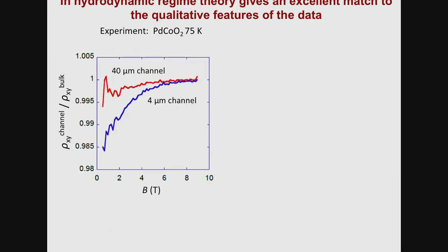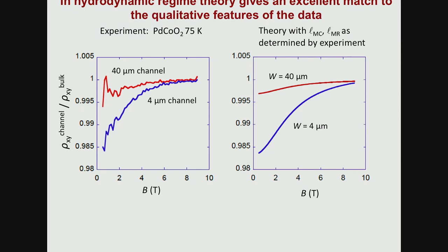He'd worked on the Hall effect, which is another thing. There's a viscous Hall effect, which is now well understood theoretically. Nabonil and Andy, who did the magnetoresistance experiments, was also doing Hall effect ones. The signal to noise is poorer for various reasons there. But again, the modified Navier-Stokes approach, field-modified Navier-Stokes approach, can get a pretty good agreement with the type of things you see. So we thought there's only one more thing to test, and this is, I think, really worth